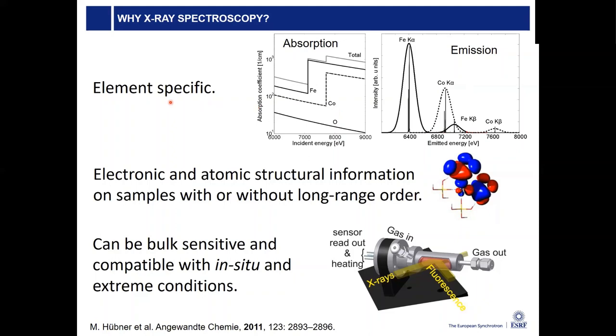And of course, it's element specific. That's very important. If you ever write a proposal for an X-ray spectroscopy beamline, you should say that you want to do spectroscopy because you need an element-specific probe of the sample. Not only do absorption edges depend on the atomic number, but also the emission lines are sensitive to the atomic number. And of course, you do this because you would like to obtain information about the sample, so about the electronic structure and the atomic arrangements locally around an absorber atom. And this is information you can look for and extract from the X-ray spectrum.